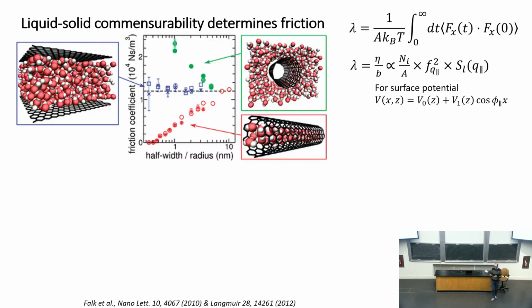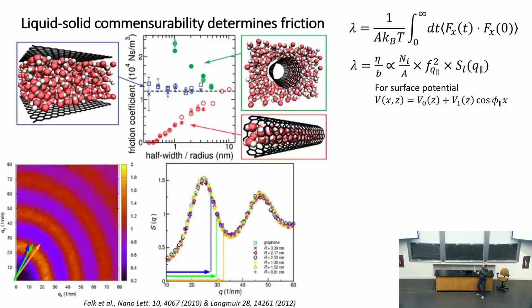A different way to fruitfully think about the friction coefficient stems from looking at the Green-Kubo formalism that relates this coefficient to the equilibrium correlation in the friction force. By crude approximations, it can be shown that this friction coefficient can be related to the number of water molecules per area at the interface, times the amplitude of the force potential at the wall, times a structure factor. This is the structure factor of the liquid. Okay, the structure factor of the liquid actually looks like this.